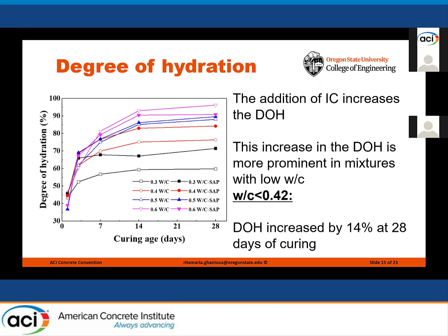So we can see the degree of hydration obtained from loss on ignition measurements on the y-axis versus the curing age on the x-axis. The degree of hydration of cement-based sample with and without SAP with 0.3 water to cement ratio seems to increase from 1 day to 7 days and then remain relatively constant until the end of curing. The degree of hydration of cement-based sample with a higher water to cement ratio show a continuous increase from 1 to 28 days. So the cement samples with high water to cement ratio indicate a higher degree of hydration as compared to the sample with lower water to cement ratio, which is expected.